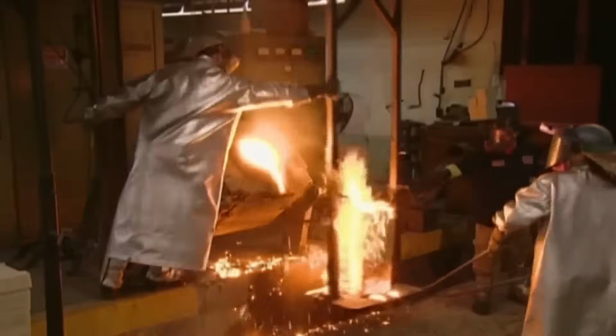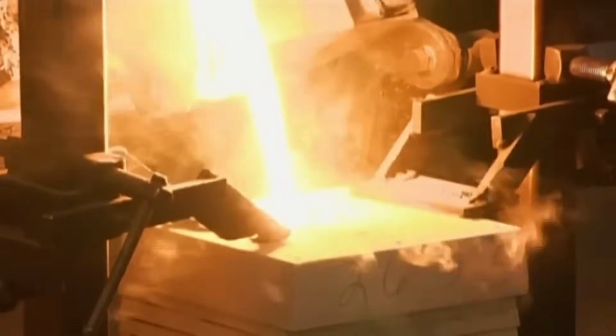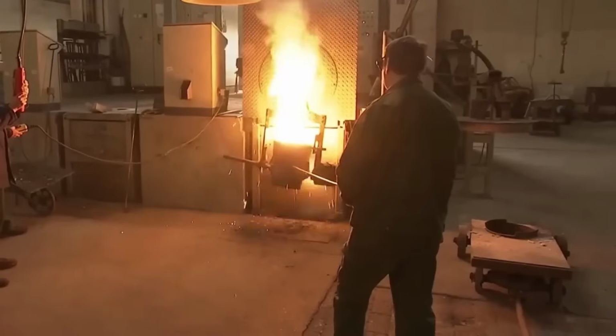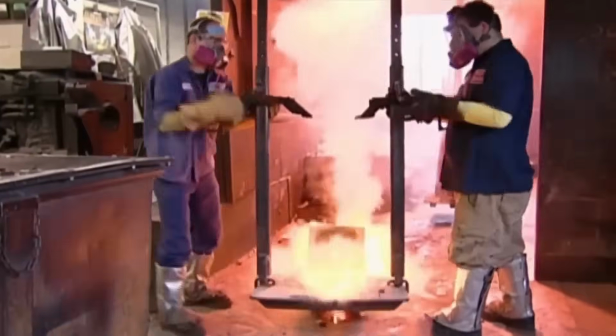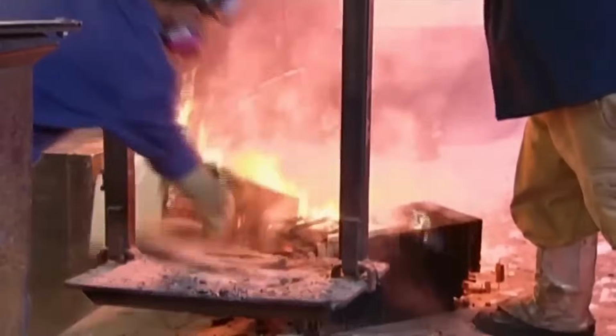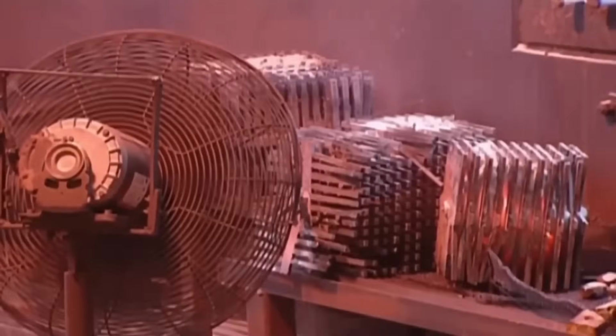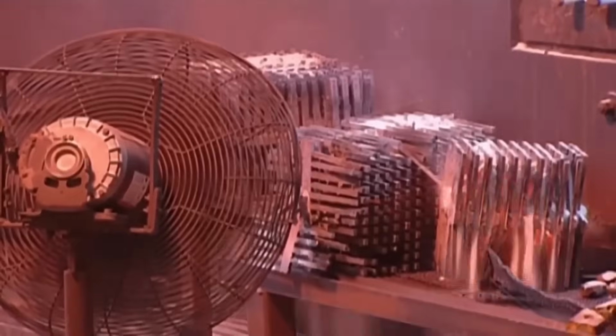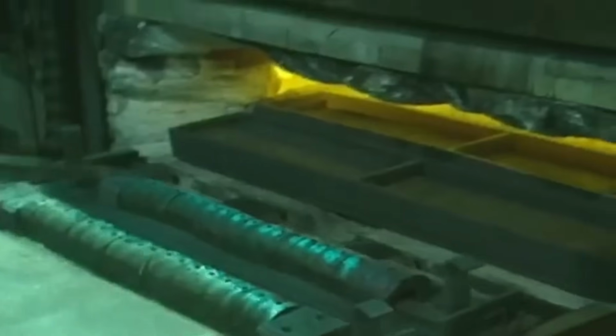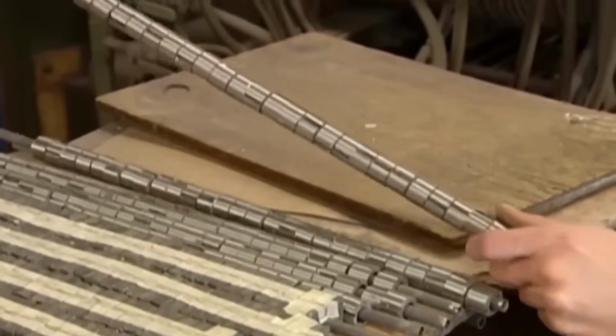Once fully melted, the glowing metal is poured into the sand molds, each cavity filled with perfect precision. Then the alloy is left to cool. As it solidifies, it shrinks a bit, so the molds are designed with tiny compensations built in. A controlled cooling system speeds things up just enough without introducing cracks or internal stress. When the alloy has completely hardened, the sand mold is broken apart, freeing a raw neodymium iron-boron ring. At this point, it still isn't magnetic at all.